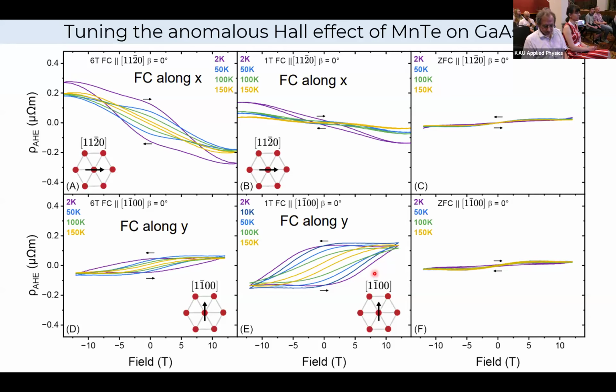Thank you for the interesting talk. I have a short question. Is it possible to add small strain to the manganese telluride grown on strontium fluoride substrate, and then compare it to the gallium arsenide substrate? Yeah, that would shed some light on which reason is responsible for this. Right, so I have to think about this. If I grow thin enough on strontium fluoride, which is something that we're doing, so the film that I showed you is actually 100 nanometers to 1 micron. But if we grow 20 or 15 nanometers, something thinner, then yes, the films on strontium fluoride will be strained by the lattice mismatch.